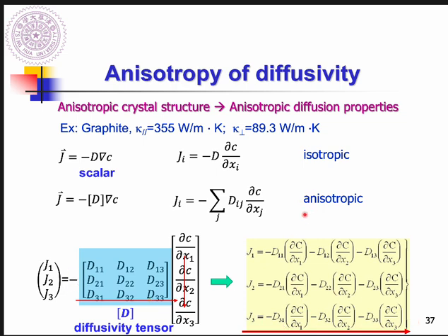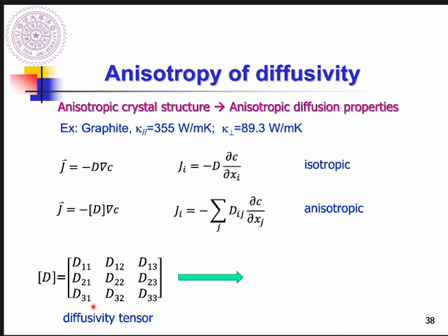So when you deal with anisotropic structures, as long as you can formulate the diffusivity tensor, that can help you easily get Jx, Jy, and Jz along different axes. It's not a big problem, but you need to have this idea. You need to know, as long as the crystal you deal with is not isotropic, you need to formulate the diffusivity tensor to express your case. Okay,